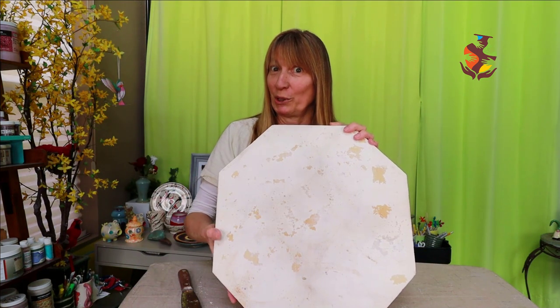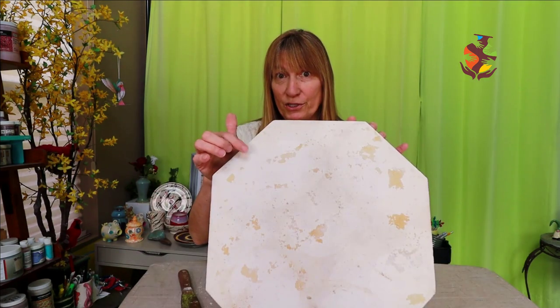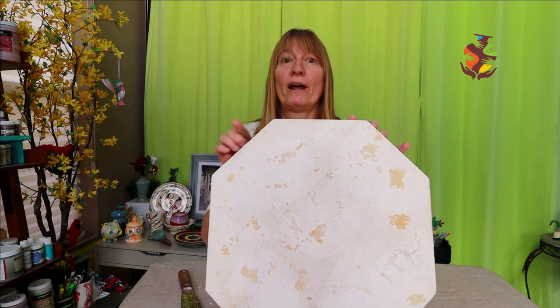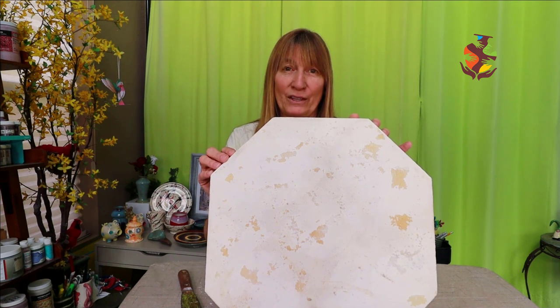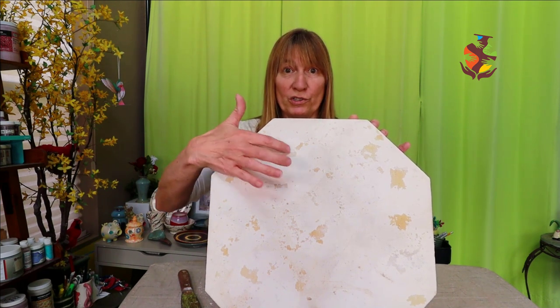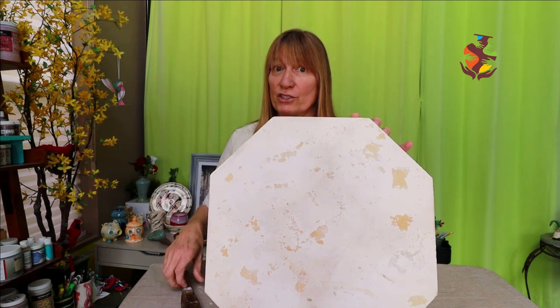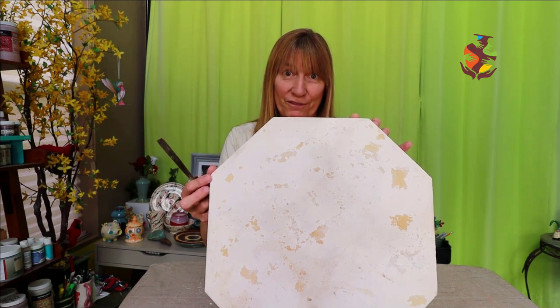Your shelves may end up looking like this. If the kiln wash is applied too thick, after a while it will flake and the flakes will fly around inside your kiln and stick to your pottery. Over time, the kiln wash will start to chip and pit like this. Then you have to scrape and grind or even chisel it off.